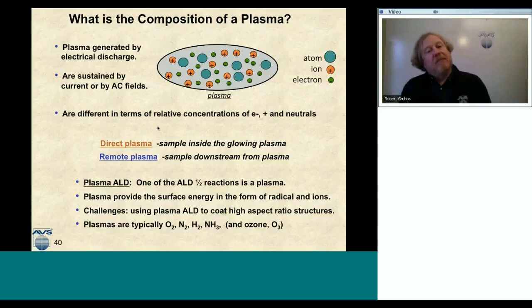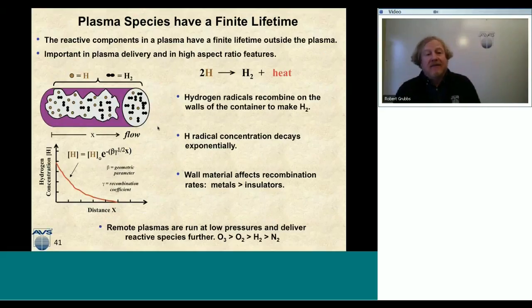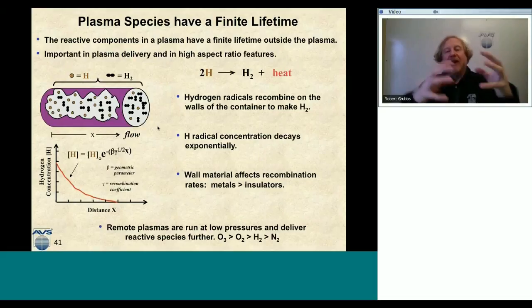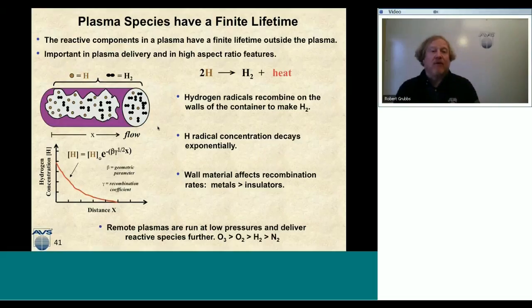Now, as I mentioned, plasma species have finite lifetimes, and because the components are only really alive, say, in the plasma itself, they're going to have finite lifetimes outside the plasma. And so this is important for plasma delivery. So as I said, in remote plasma, they usually run them at lower pressures so that the mean free path is longer, and I can deliver these radicals to the surface.